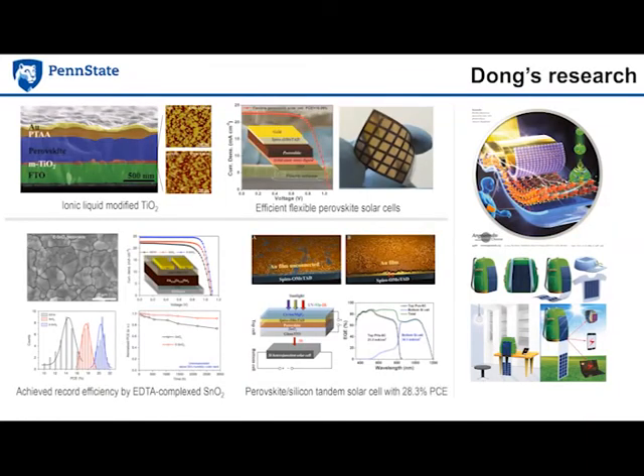So here are the highlights of his research. The first typical work is to optimize the surface of the tin oxide, titanium oxide electron transport layer. He used an ionic liquid to improve the mobility and charge transfer properties in these layers. And again, he got very good device performance from this optimization, which reached the record back in 2016. And later on, he came up with the idea of using a solid state ionic liquid to replace these rigid layers like titanium oxide.